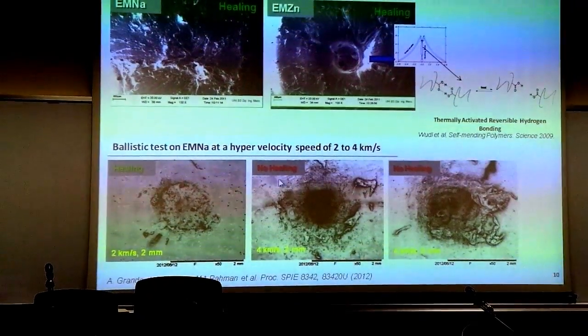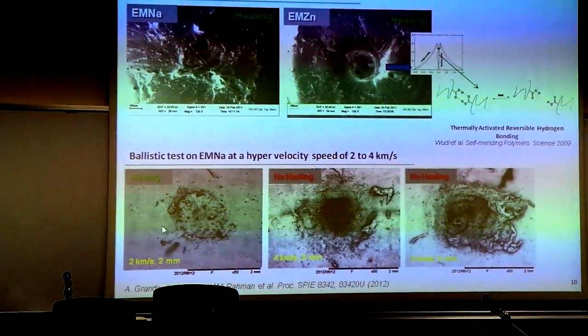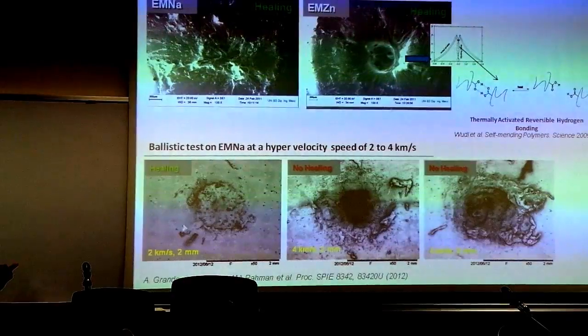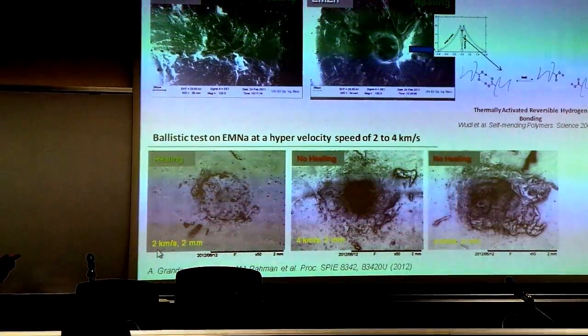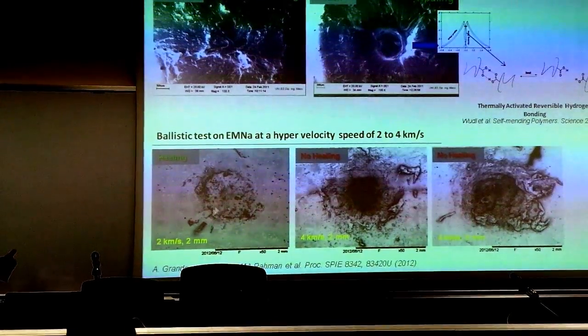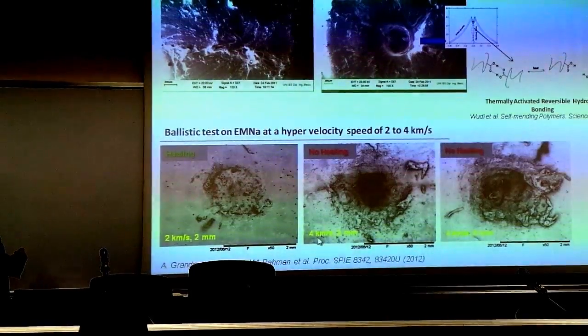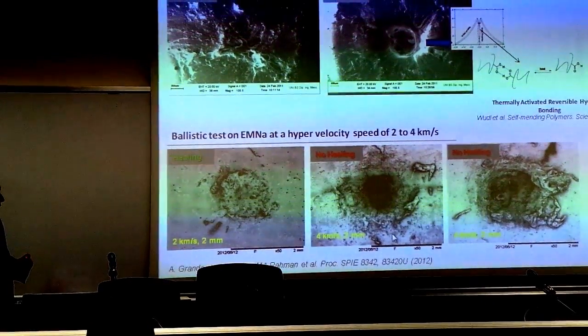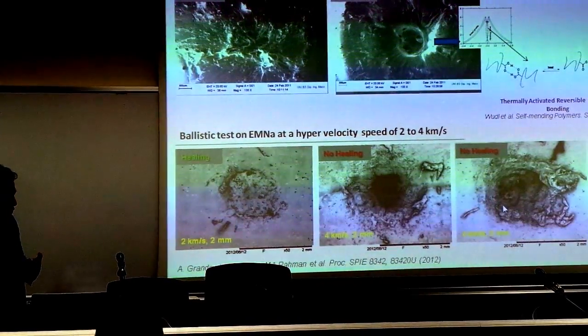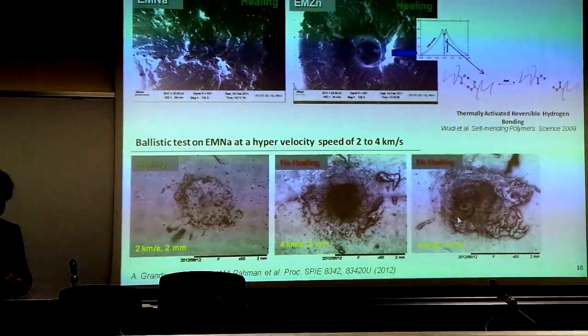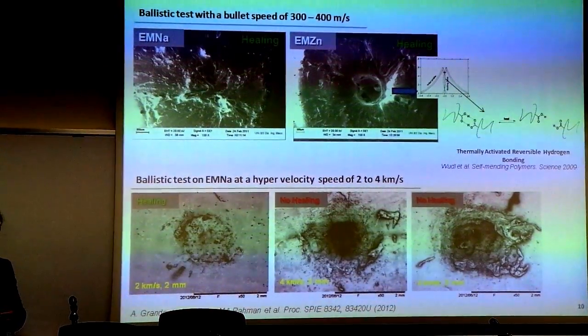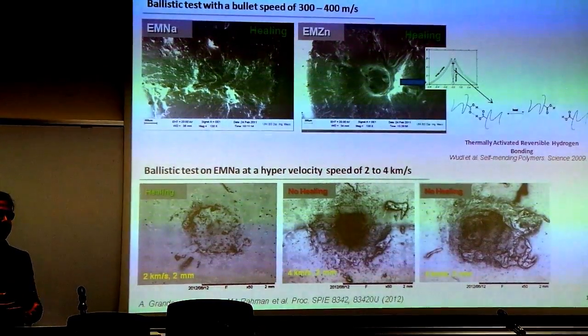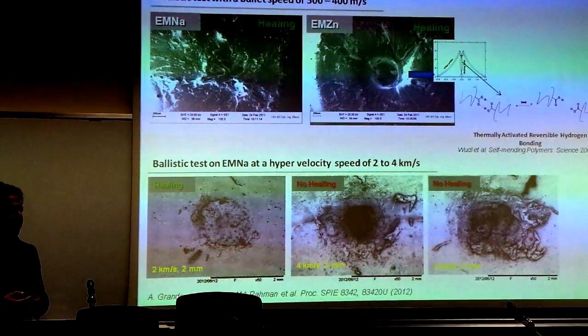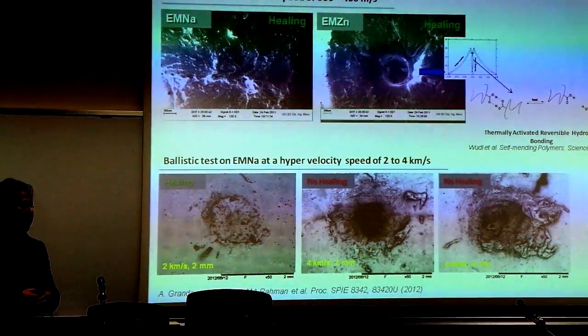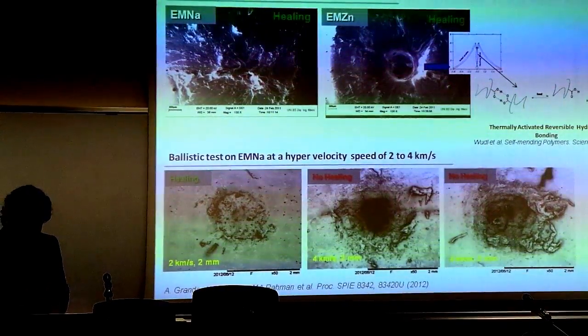In these micrographs, you can see that the ballistic self-healing of ionomer was tested when the bullet speed was 2 km per second. The material showed self-healing. But if we increased the speed, the material did not show the self-healing. That means that there are some physical parameters such as the size and shape of the bullet or the velocity of the bullet that also significantly affect the self-healing ability of ionomers.